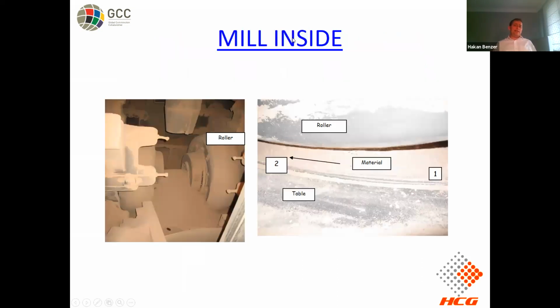That's why, as I said, we started to crash stop the mills, and we are taking samples around the grinding table from different regions to address first the grinding action and to understand the mass balance within the system. Therefore, we have been using an iterative mass balancing technique to find the best flow rates. This has been tested with CFD studies, and this is the state of the art of the group in order to sample the vertical roller mills.